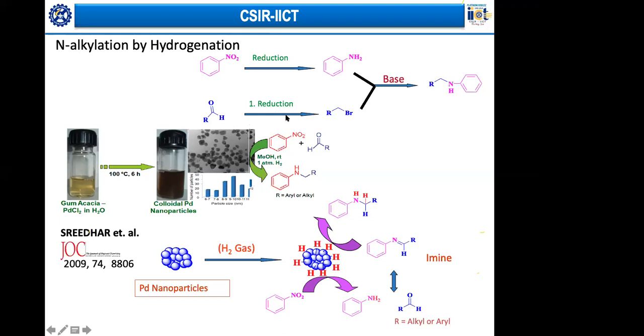Another very important thing about these gums is that they are soluble only in water. And here we are talking about methanol. So you can see this mechanism here. These palladium nanoparticles are coated with gum as a surface protection, and once you calcine it, their pores develop. So when we put a hydrogen balloon to heat, they form palladium hydride bonds, and this acts as a catalyst for the various organic reactions. So this palladium hydride acts as a catalyst, and that is how you end up getting these catalytic products. So the advantage, as you can appreciate here, is that in the conventional case you generate waste along with the product, but in this it's very easy.